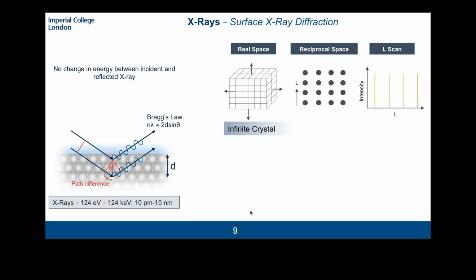But here you're basically relying on Bragg's law, where if you have certain conditions for the incident X-ray, you can reach a condition where all your reflected X-rays are basically in phase, and you can have a much brighter intensity because of this constructive interference. If you meet those conditions, and those depend on Bragg's law, which is a function of d and this angle of incidence here.